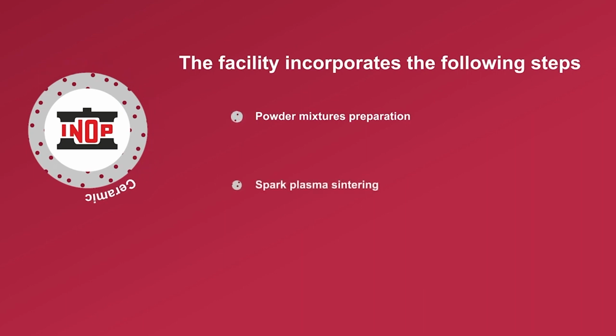Spark plasma sintering. This step starts from assembling the high-strength graphite tool setup for sintering. The powder mixture is poured into die in inert atmosphere. Then, spark plasma sintering is done in vacuum or inert atmosphere. The maximum sintering temperature is 2200 degrees Celsius and maximum compacting force is 250 kilonewton. The maximum size of sintered part is of 60 mm diameter and 20 to 25 mm thickness, depending on the powder's apparent density.